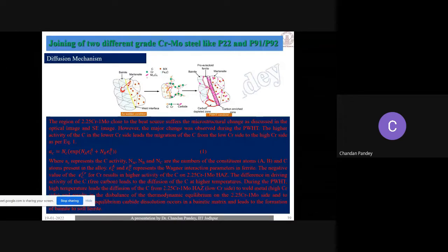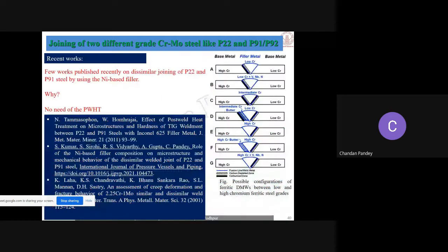And when carbon diffuses from that point and comes along that boundary, here there is a presence of chromium, and it combines with the chromium and forms a layer of chromium carbide in a very narrow region. So in a narrow region, in about microns, we get the formation of both the soft zone and the hard zone. That hard zone will not create the problem, but the carbon-depleted soft zone facilitates crack initiation during service. So that is the problem during dissimilar joining and their service condition.